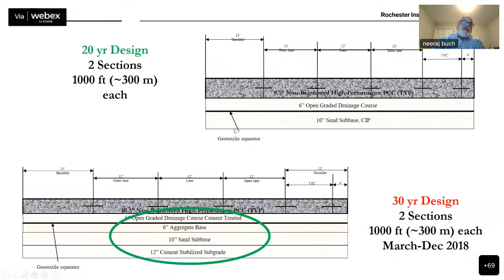So there was a 1-inch difference between the slab thickness of the regular pavement versus the long life pavement. And then the foundation layers were significantly different and significantly thicker. So the cross sections were significantly thicker than the regular, the 20-year design. So there was an open graded drainage course that was then placed on an aggregate base, followed by a sand subbase. And then the first 12 inches or 1 foot of the subgrade was cement stabilized.